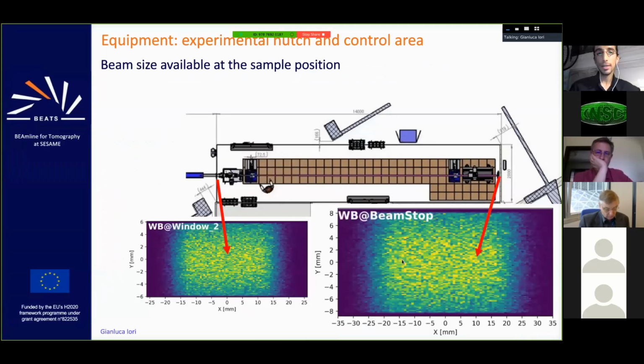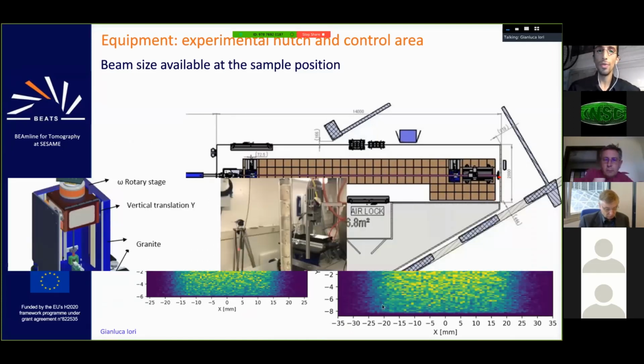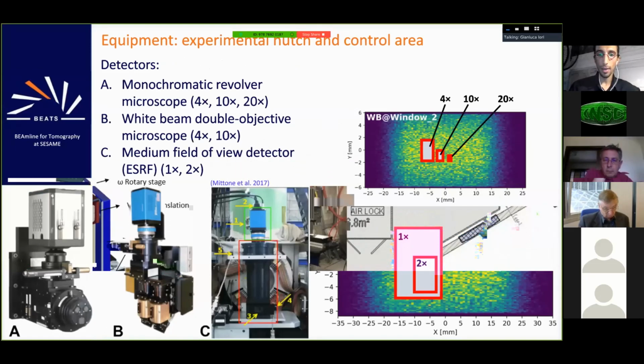I was saying that we use this propagation to tune the beam size. These are snapshots of the beam at the entrance and exit of the experimental hatch, and you see that for small samples, we can work close to the entrance where we have 30 millimeters of beam. For larger applications, where we need a large field of view, we can move the sample towards the end of the hatch and have 45 millimeters width of beam. So this more or less defines the maximum sample size that we can have.